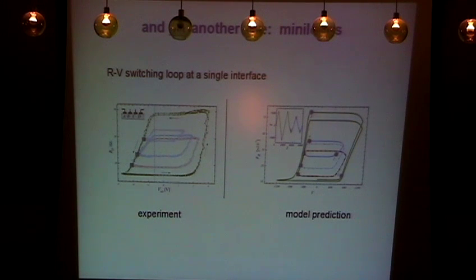That's right. Okay, so what we learned from the first model was that the interfaces were important. Why do you need this three-layer structure, like the two interfaces and the buffer in the middle? Well, it turns out that if you use 2 or 1, which is what we did as the initial step, you don't get a switching that you can put in contact with any experiment. So the first thing that came clearly from there is that the three layers matter. That already had some good comparison with the experiment, so it told us we are on the right track.